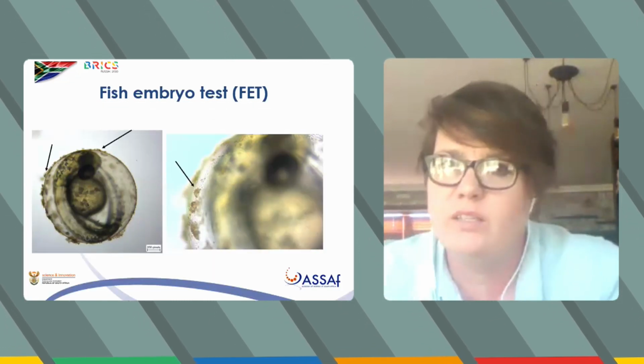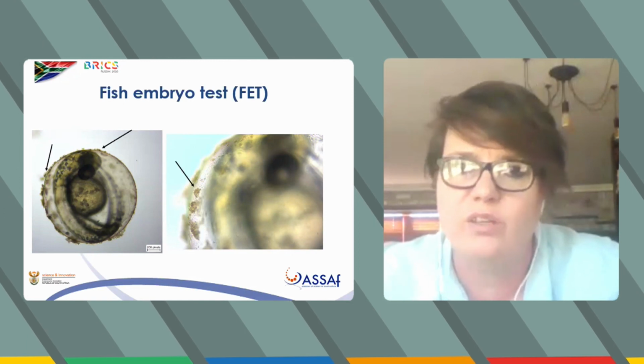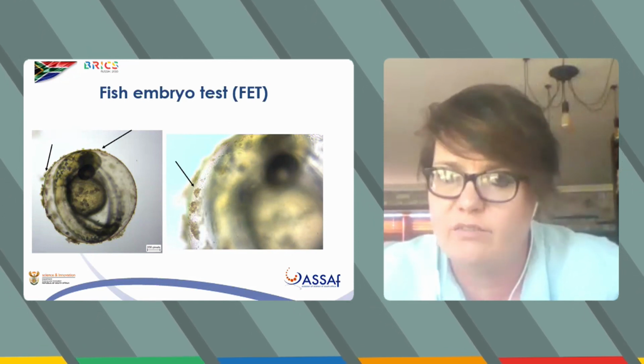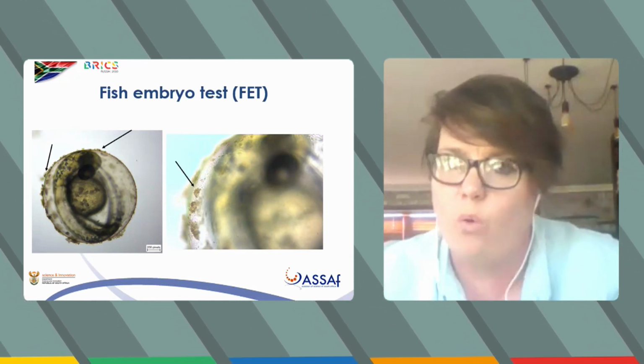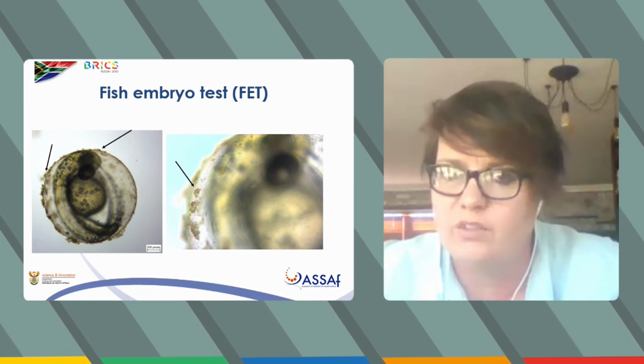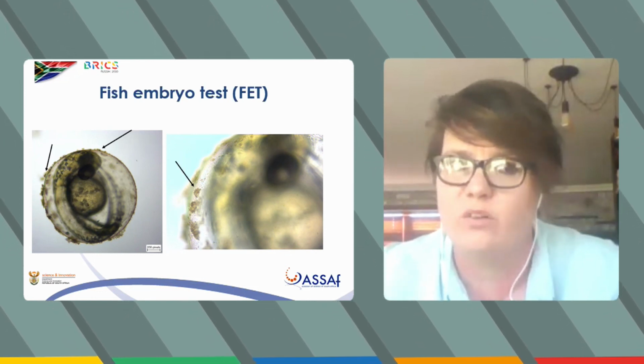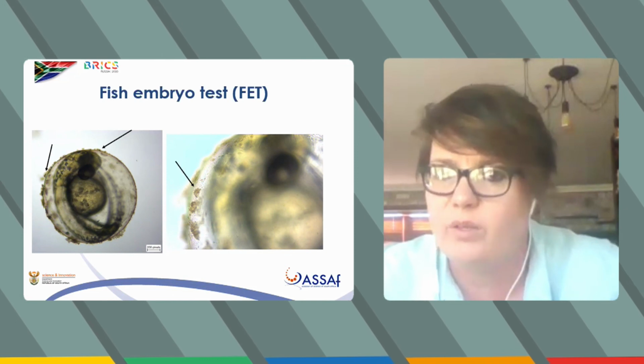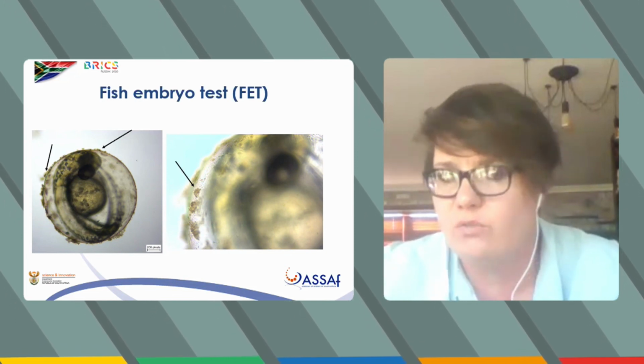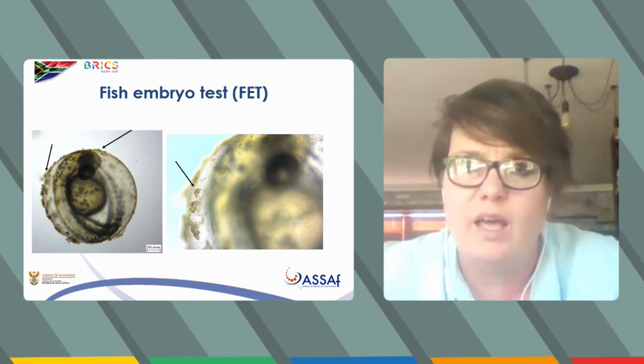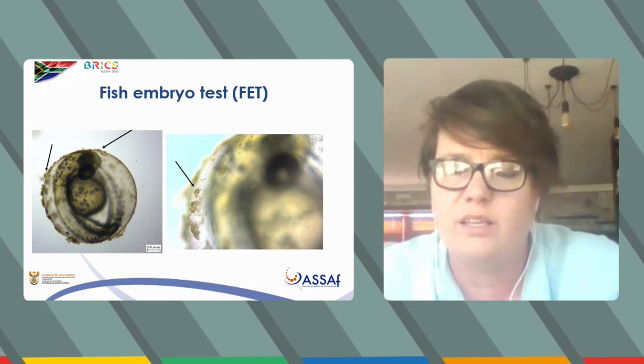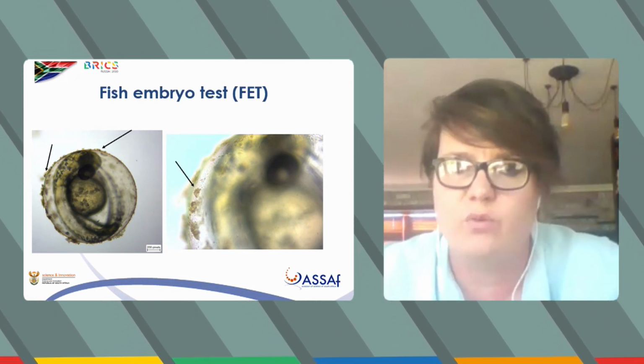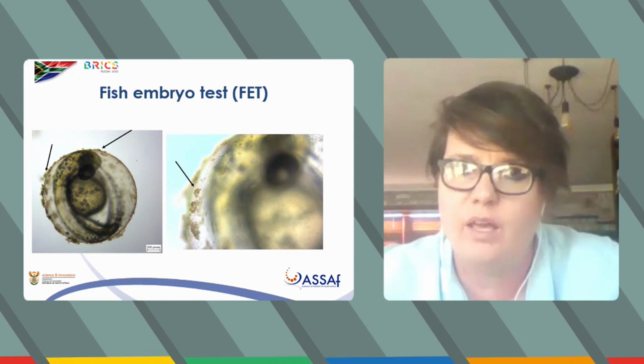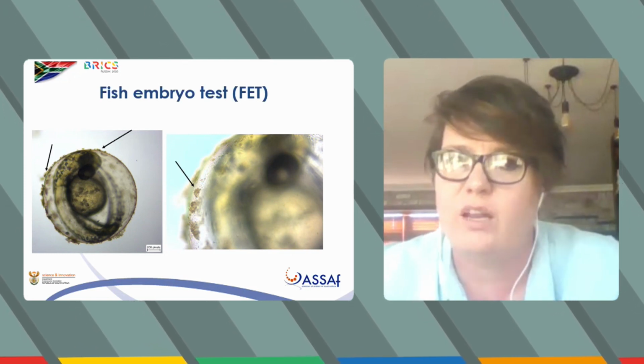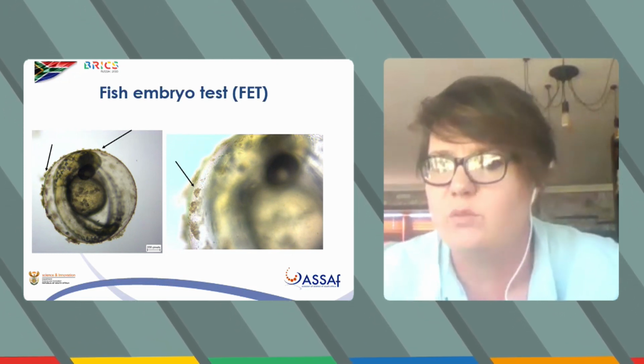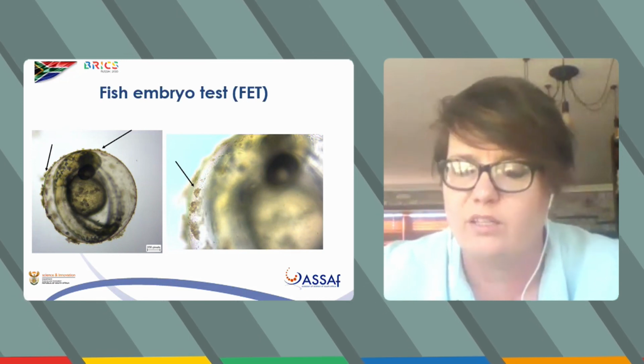One of the things we did notice, and just to point out to you, is the chorion is a negatively charged compound with pores, and the fish requires the chorion to be protected, obviously, from the external environment while it is developing, but it also needs to respire through these pores. And it's not part of this study, but in other studies we've done on 3 functional groups of quantum dots, we actually were able to see that the fish is no longer able to respire because these pores become blocked with aggregates of nanomaterials.